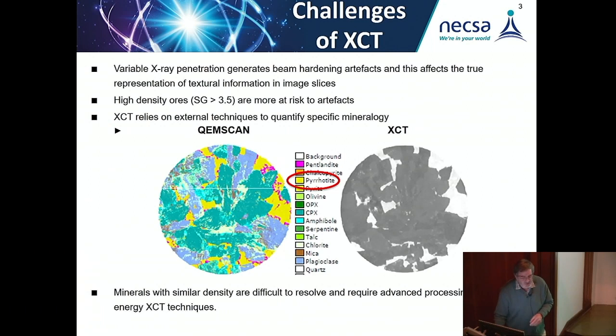These are generated when the softer X-rays are captured by the material in some areas, but on the edges, sometimes those softer X-rays penetrate through. So effectively, it seems that the edges of the sample have a brighter or higher attenuation of the beam, which you can account for.